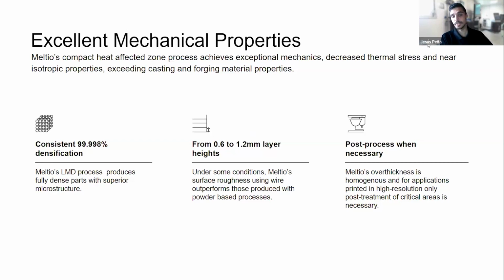Then also, under some conditions, the roughness is important for our customers. In case they need to focus on a low roughness because they don't want to machine, they don't need it for the process, they just go with smaller layer heights and are able to achieve some Ra close to 12, 15, 18, depending on the material being printed. And of course, in case any kind of post-process is necessary, the customer can just select between the processes that we recommend.